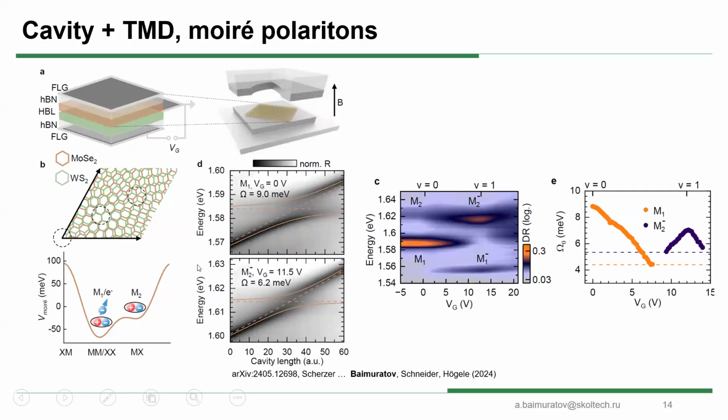But for M2, the situation is completely different, because we have, let's say, electrons like a lattice of electrons, and M2 is delocalized from this lattice. And you see that M2 now does not show this abrupt step. It just slightly changes in energy.